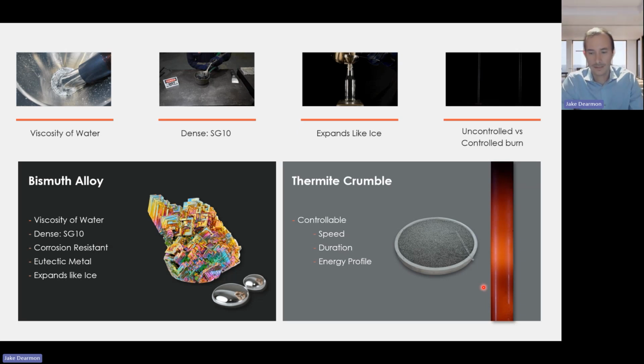Now, traditionally thermite's been around for over 100 years, and it wasn't very sophisticated for a long time. They used it downhole, they used it on railways to actually weld materials together, as well as military applications where the only thing they wanted to get out of the thermite was to make sure it burned. Obviously, we have to control it a little bit more. So in the next video on the left-hand side, we'll see what happens if you just take normal thermite and put it inside of a heater and ignite it, and it does bad things to the heater. But here at BiSN, we spent the last decade doing a lot of research into thermite, and we actually make all of our thermites now in-house. We're able to sort and go through our quality control process, really refine the particle size distribution of the thermite, put different additives into it to control how it's burning, how much energy it releases. So we were able to tame that really high energy density source into a useful application for us.